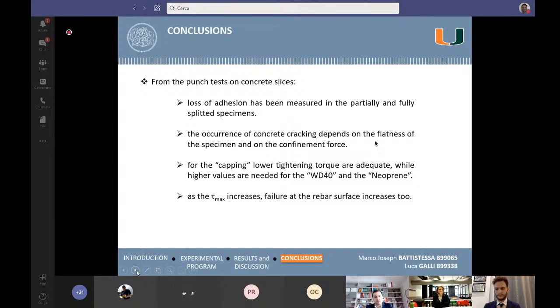For the capping, that is also the configuration that allows to obtain perfectly planar surfaces of the slices, a lower tightening torque has been found necessary to avoid the concrete splitting, while higher values are needed in case of WD-40 and neoprene configurations. Also, the capping is a procedure that is largely used in the compressive test, so it might be used for the same purpose also in the punch test, since it does not require the time-consuming practice of the specimen preparation.